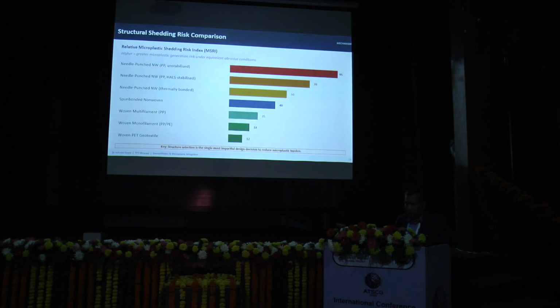So we can move slightly faster. This is a comparative assessment of the different types of structures and their capacity to release microplastic. Needle punch non-woven fabric is considered to be the poorest, and it is the most vulnerable to microplastic generation, and the best is the woven material. Wovens are considered the best because the leaching of microplastic is reduced by the usage of woven materials.